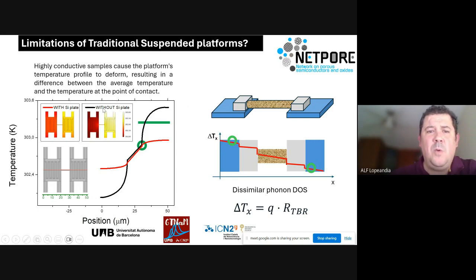The black curve is the one without a silicon plate, without a diffusive plate underneath. The first problem that we find is that we have a depression of the temperature at the point of contact of the nanowire. It essentially means that we measure an average temperature in the coil, but we have the wire at a different temperature at the contact. Then, okay, we can only access the average temperature. This is a major problem, no? Because we do not measure the real temperature drop in the sample. And at the end, if we want to measure thermal conductivity, we need to get the temperature drop in the sample that we are measuring.